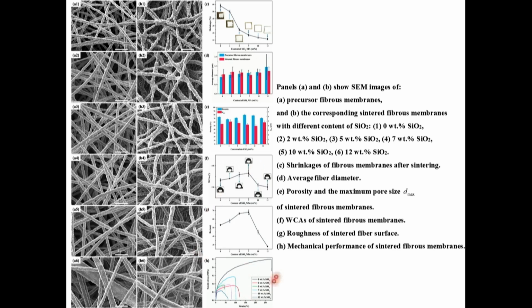There is also some information about stress-strain behavior. So you can see that this is essentially initially elastic, then it's hyperelastic. This is a stress-strain curve, so it's the hyperelastic part, and then in some cases you have a long plastic branch, and in some cases the fibers become stiffer, and you have an abrupt catastrophic breakup in stretching. But all in all, these are pretty robust fibers which we made, and I'll show you some additional tests of these fibers, not only in stretching, but also in abrasive action and chemically aggressive media and things like that.